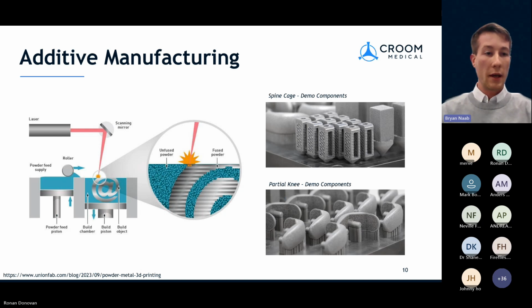I'll focus mainly on powder bed fusion technology, since this is what most metal medical devices are manufactured with. In this process, essentially a very thin layer of metal powder is distributed on a substrate known as a build plate, and a high power energy source such as a laser or an electron beam then traces that two-dimensional slice, that pattern that was extracted previously from the model, onto the build plate. And that process is repeated continuously until the three-dimensional part has been reconstructed.